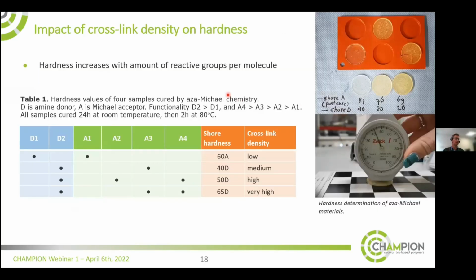So what we found is that we could increase the hardness of the materials that we make by increasing the amount of reactive groups per molecule. And this makes sense because if you have more reactive groups, you can make a more densely cross-linked polymer network. And usually in this way, you end up with harder materials. And this is what we found. So here we have some anonymized results in which the functionality of diamine D2 is higher than the functionality of diamine D1.